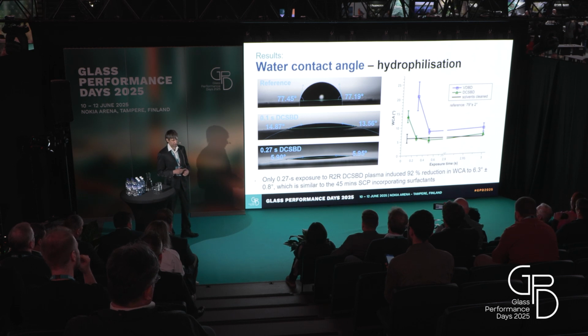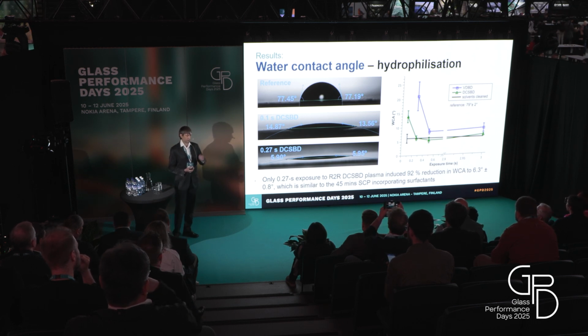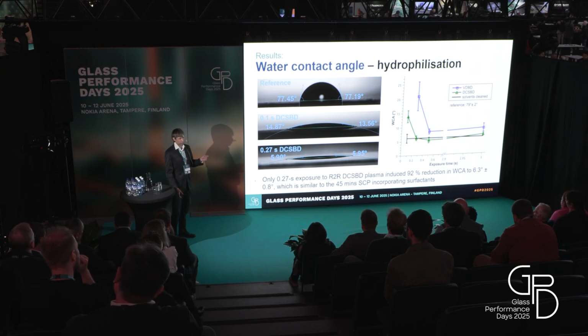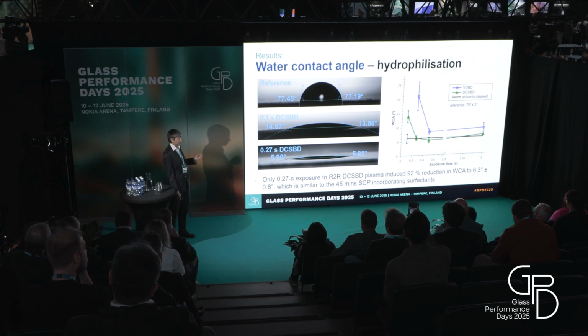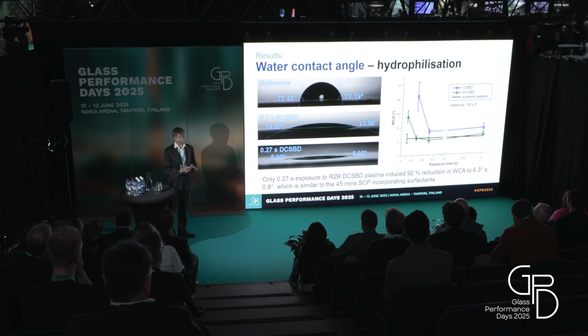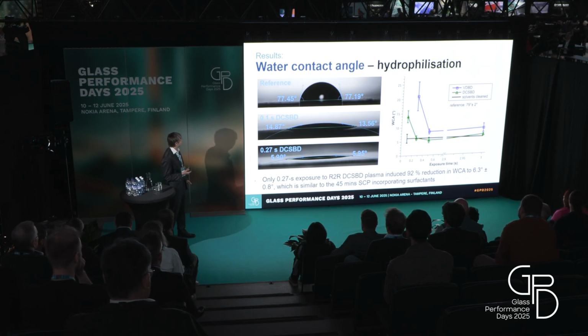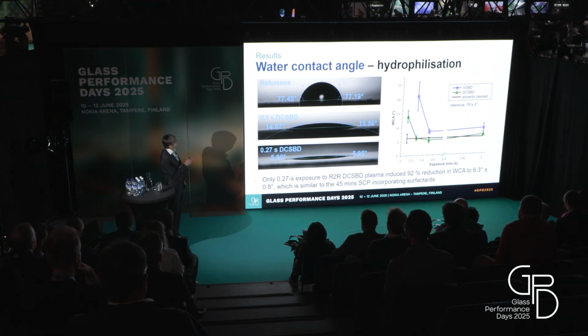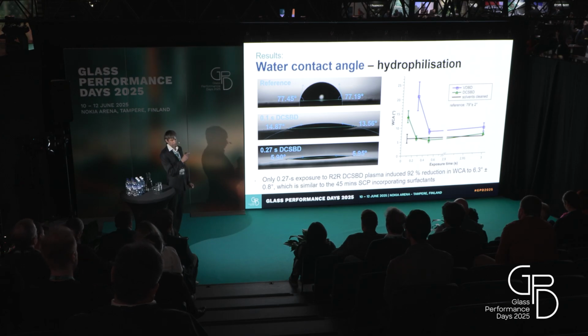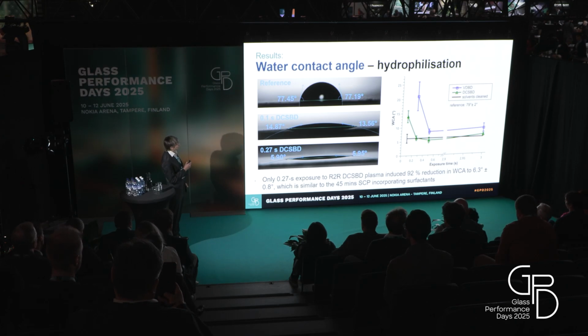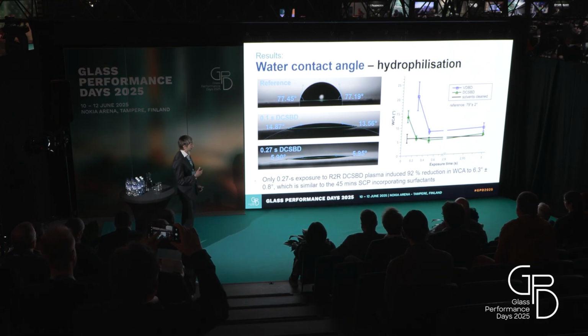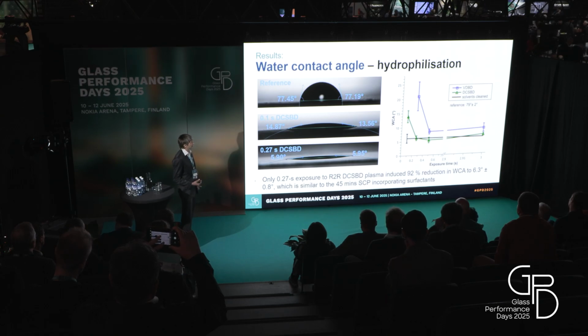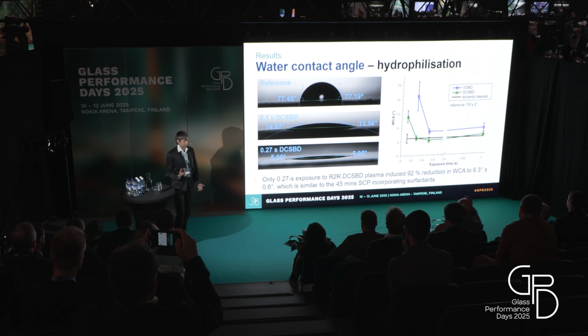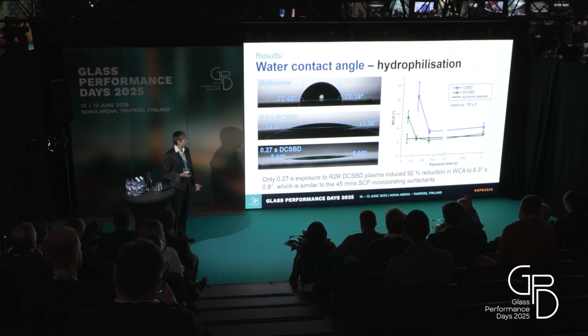So first, the very fast method we use for the change of the surface free energy is to make a drop of water on the surface, and if the surface energy is higher, it can spread more, which can be beneficial for spraying techniques that can save the material dispersion needed for spraying, because you can cover a larger surface faster with fewer drops. And even just 0.1 second dropped the contact angle of this drop very low. And after increasing the treatment time, which you see on the graph on the right, increasing the treatment time doesn't induce more decrease of contact angle. So we chose that very short treatment time, which we were able to do with our DCSBD reactor, is sufficient for our experiments.